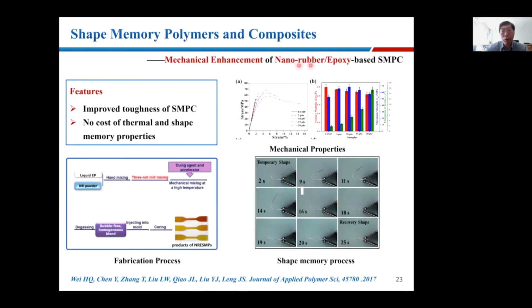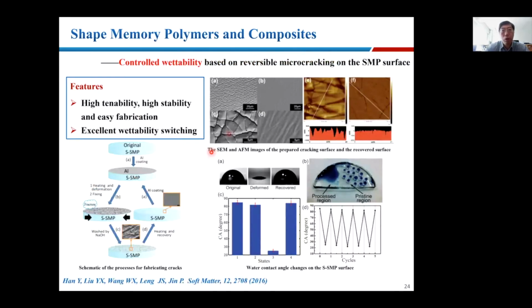The reason we're using nano rubber is that nano rubber can also improve the toughness, but does not compromise the thermal and shape memory properties. This is another example, for micro cracking. With the shape memory polymer, we can make a film with some cracking, but when you're heating, the cracking can disappear. You can see the contact angle: that is the original shape, and that is deformed to keep the shape at low temperature below the Tg. After heating above the transition temperature, the contact angle will change back to the original one. With this, you can simply control the wettability.